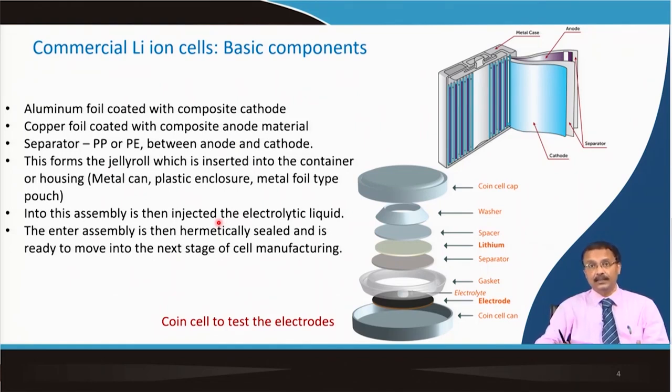Then the entire assembly has to be disconnected from the ambient, because if moisture is present, then moisture reacts with the salt, which is LiPF6, and it will create hydrofluoric acid, and this hydrofluoric acid is corrosive. So, that will deteriorate the cell performance. So, it is hermetically sealed, and this is ready to move to the next stage of cell manufacturing.